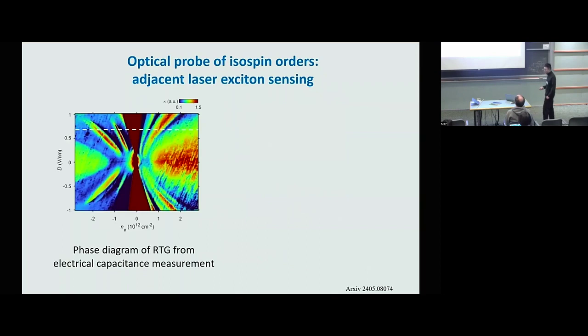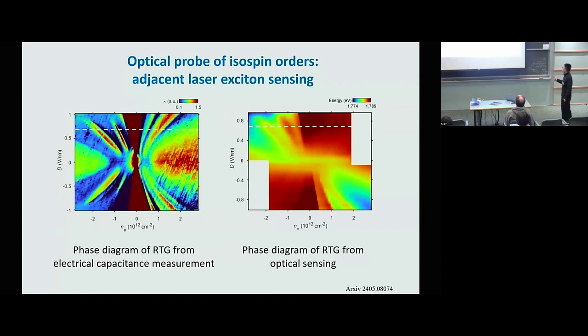So here, I just use the simplest way to demonstrate the work because it works in experiment. In this plot, we are seeing a phase diagram of the RTG, rhombohedral graphene, from electrical measurement. This phase diagram is consistent with our previous studies, so we'll just briefly go over it. We can see some lobes on the hole side and some transitions on the electron side, and they are coming from the isospin orders. And here is the same device, but we probe it with our optical sensing technique. And we can see that, again, it fully captures all the information of the isospin orders. So on the electron side, we see two sharp transitions.